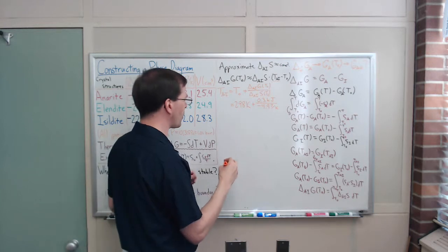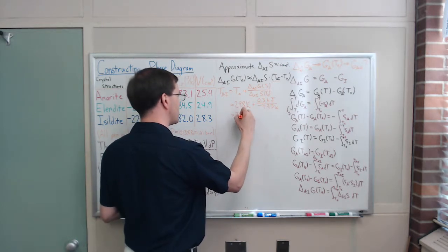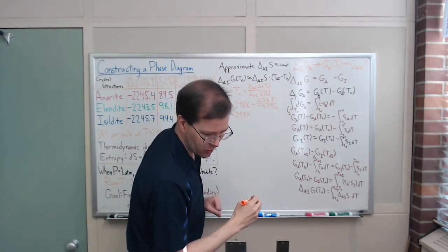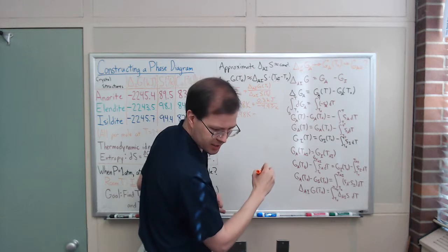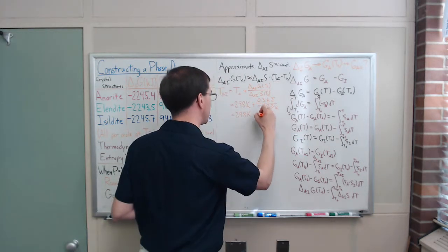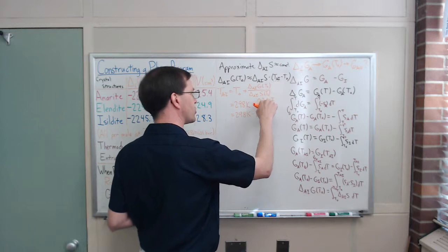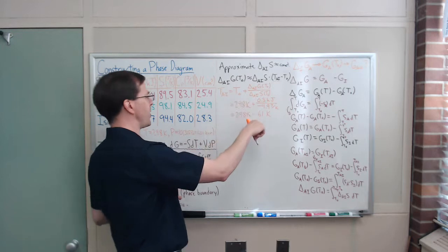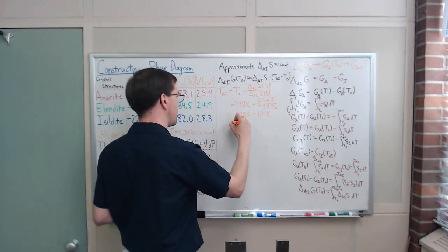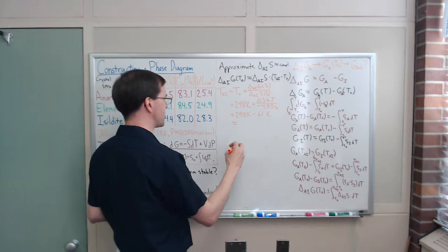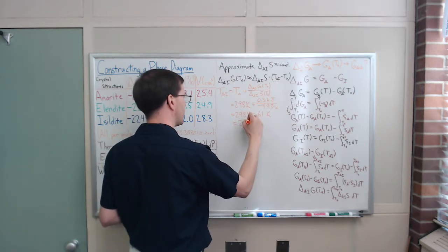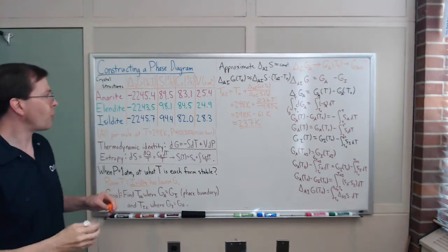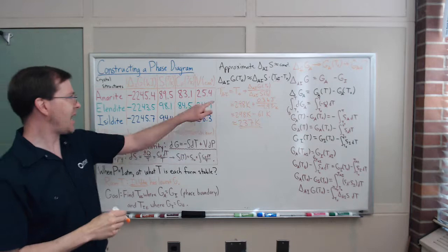And when I work this out, this comes out to be 298 Kelvin, and then, when I do that division, minus 61 Kelvin, because this is kilojoules, so that becomes 300 joules in the numerator. 300 over 5 is about 60. That seems right. So this is approximately 298 minus 61, which gives me 237 Kelvin. So there's my answer for that first temperature, the T AI.